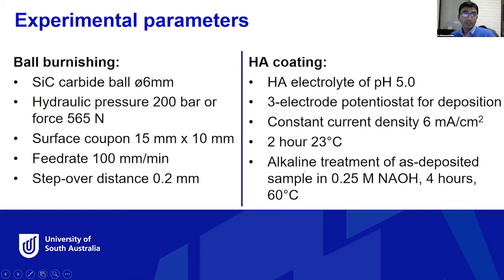After the electrodeposition of the HA coating on the sample, we did an alkaline treatment in a 0.25 molar sodium hydroxide solution for 4 hours at 60 degrees centigrade. This is because the HA is generally formed as a calcium phosphate based coating, and it becomes very porous and amorphous. So we use the alkaline treatment to convert the biphasic coating into the complete HA coating.